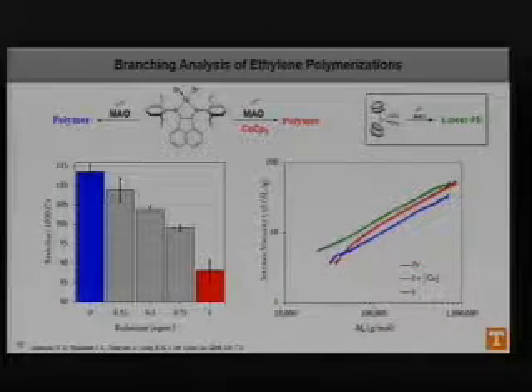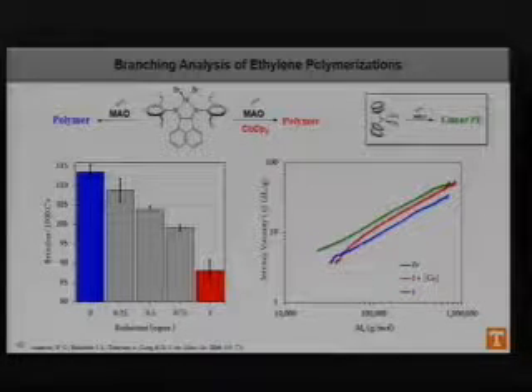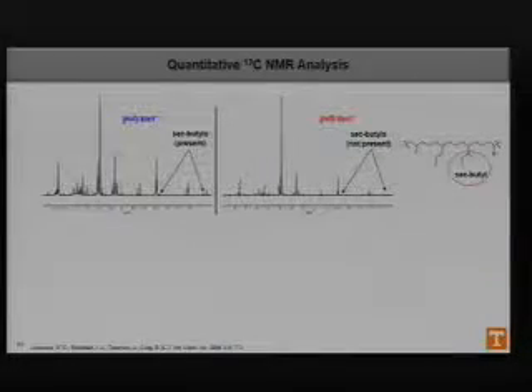So to go one step further and try and provide some more information as to what these polymers actually were, we turned to quantitative C13 NMR analysis, where essentially we found that these two peaks correspond to sec-butyl branching on a polymer chain. And I have a picture of a sec-butyl branch right over here. And in the reduced species, they're not really present anymore. The reason that this is significant is because this is the smallest form of branch-on-branch structure that can be identified via NMR. So this is actually the beginning of a hyperbranch structure being formed, and we've been able to actually eliminate this using this reduced catalyst.